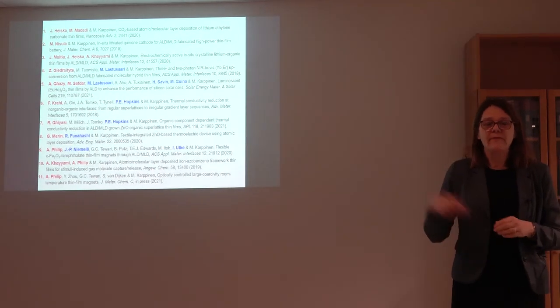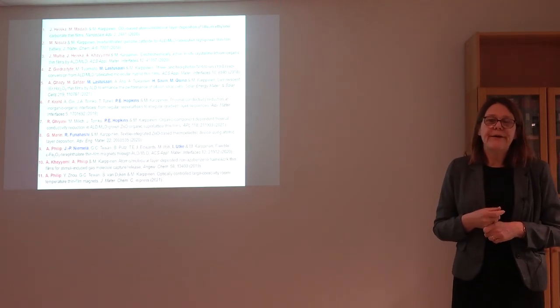We coated with different thicknesses, I think we had three different thicknesses, 40 nanometers, 50 nanometers, and 70 or something like that. With the increasing thickness, the enhancement increased a little bit, but all were increased compared to the uncoated. So it was a promising result, though totally not optimized for any parameters, but the concept works. It was considered quite a good improvement, 3%, because solar cells, at least to my knowledge, have already reached the highest conversion efficiency with all the possible tricks, so there is no other way to enhance anymore.